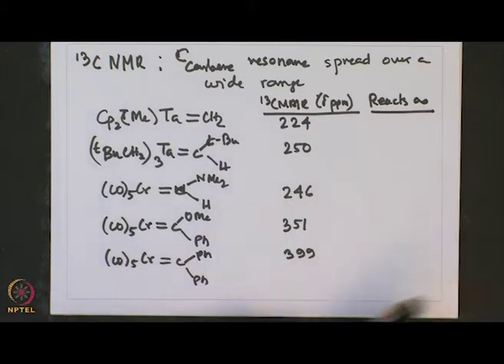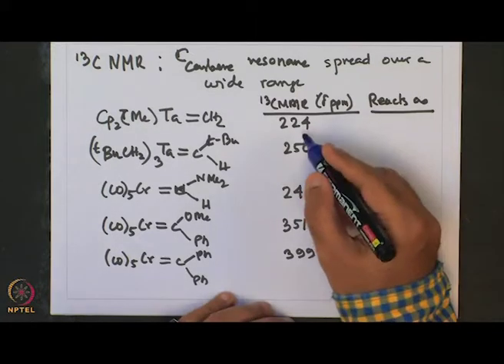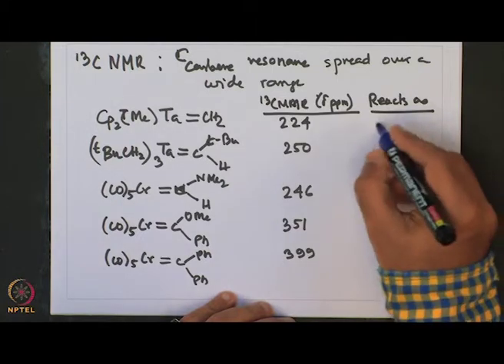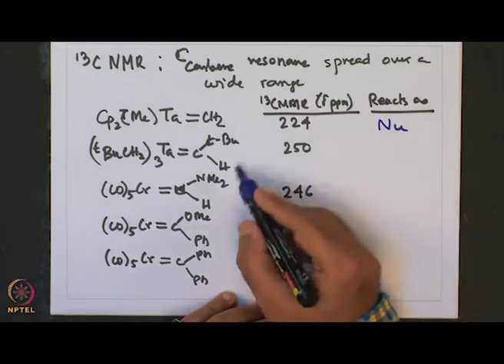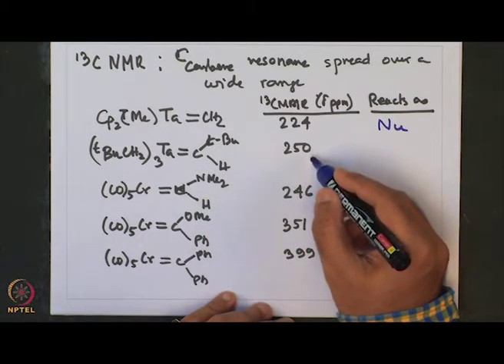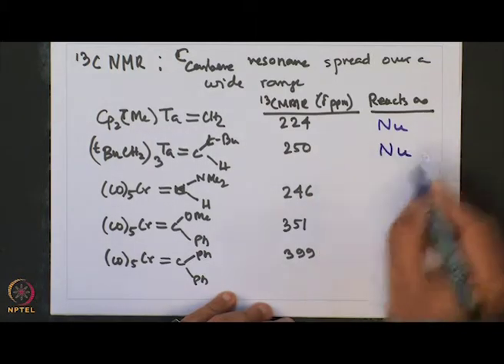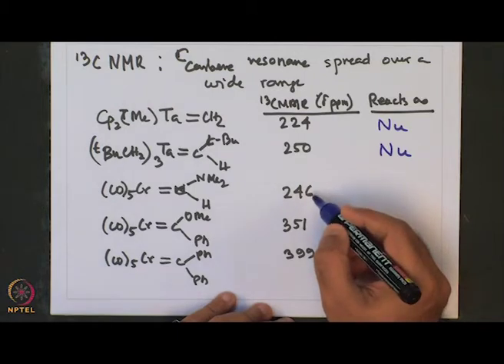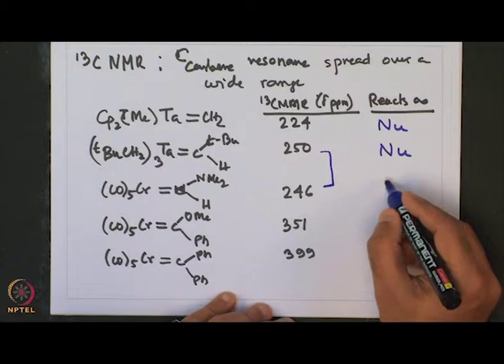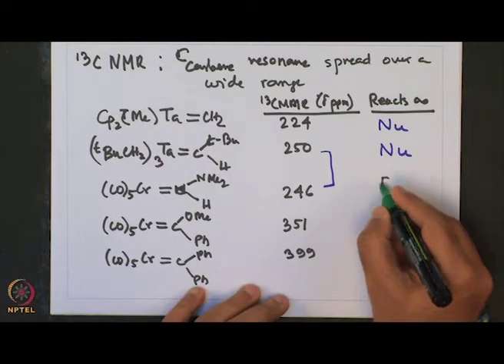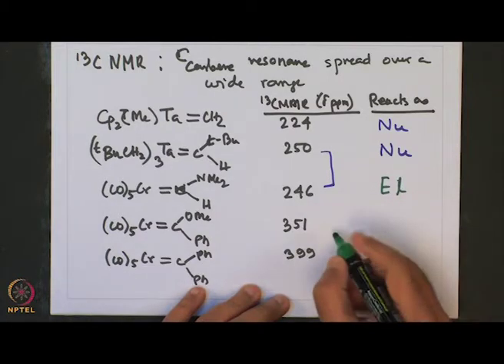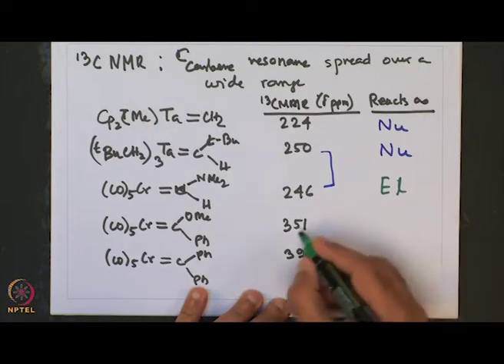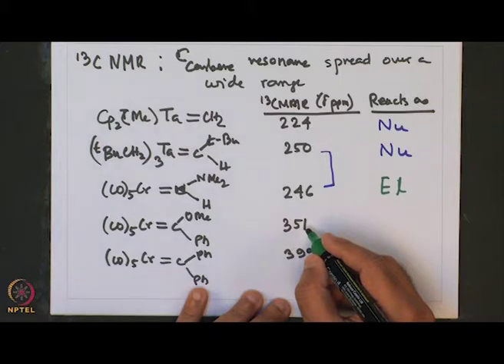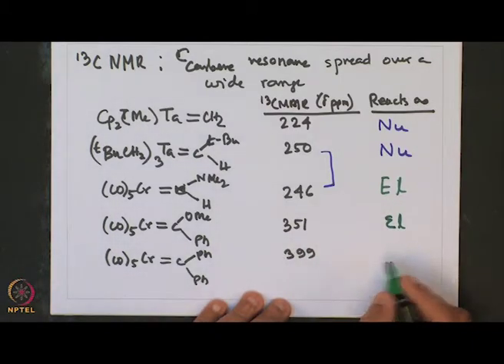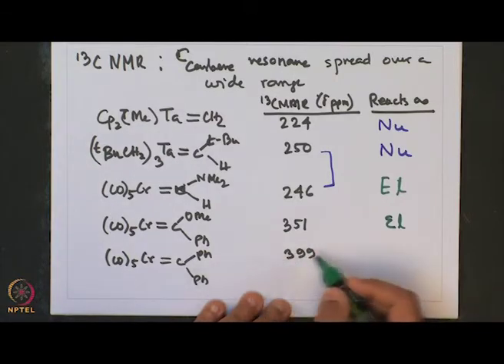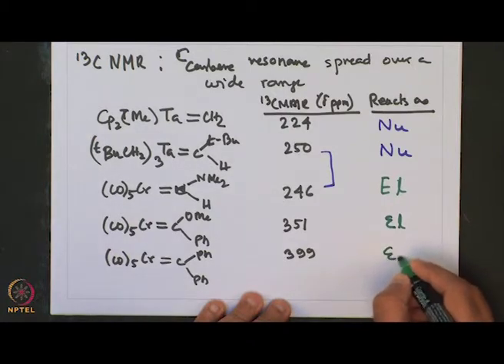For example, this Schrock carbene having a chemical shift of 224 ppm in carbon reacts as a nucleophile, whereas the tantalum one, which also has a very close chemical shift of about 250, reacts as a nucleophile, whereas this Fischer carbene, which has exactly a similar chemical shift, behaves completely differently and reacts as an electrophile. And this other Fischer type carbene appearing at a very high carbene resonance of 351 also behaves like an electrophile, and the chromium carbonyl appearing at 399 also reacts as an electrophile.